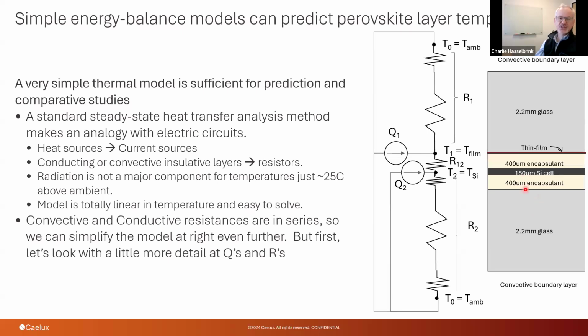This is a little bit different situation than if you have a single junction perovskite and there's no silicon cell underneath, and then that portion of the spectrum may not be getting absorbed. So the current represents how much power is being absorbed by the cell in this circuit analogy. And the resistances are accounting for the conductive resistances in the encapsulant, glass, and in this convective boundary layer above. This is actually by far the dominant resistance in this type of analysis.